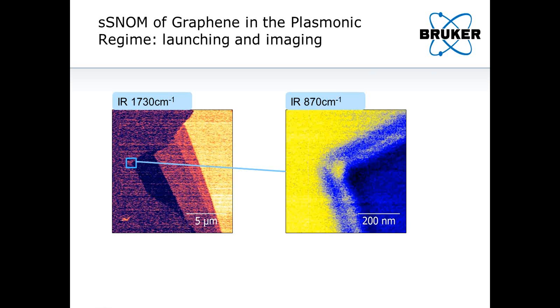So what this image shows is that the plasmon is clearly observable, and the length scale of this plasmon is very small—it's basically around 140 nanometers.